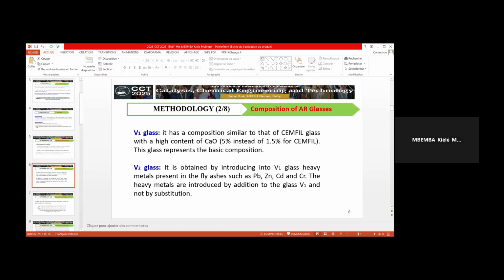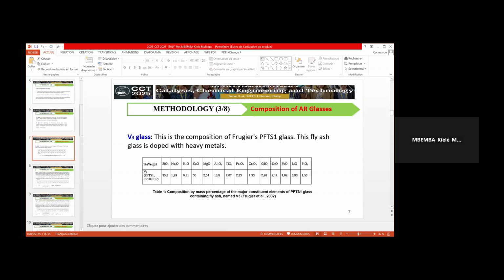V1 glass has a composition similar to CEMFIL glass with a high content of calcium oxide. In V1 glass, we have 5% of calcium oxide instead of 1.5% for CEMFIL. So this glass represents the basic composition. V2 glass is obtained by introducing into V1 glass the heavy metals present in fly ash, such as lead, zinc, chromium, and cadmium. V3 glass is the composition of the fly ash PFTS1 glass. This fly ash glass is doped with heavy metals.